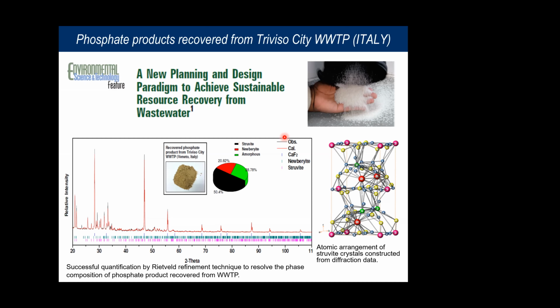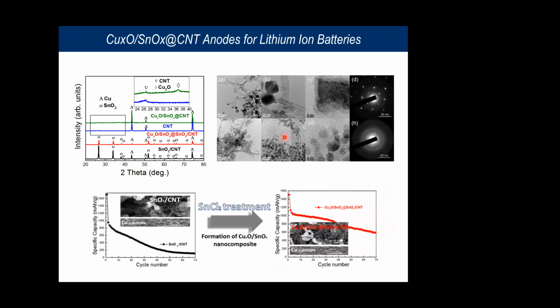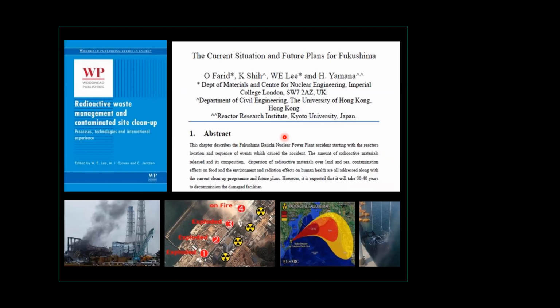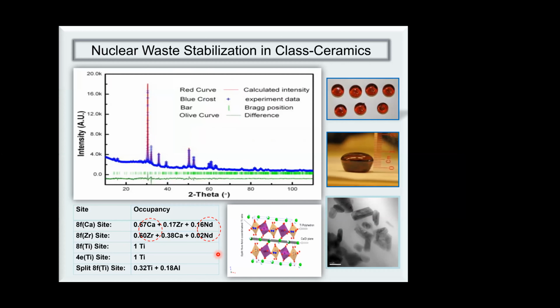And again, using quantitative X-ray diffraction will help you to know how good the recovery of struvite is. We also use this technique to work on a lot of battery materials. It's not necessarily relevant to the environment, but I'm just telling you that anything relevant to minerals, at different scales, at different applications, X-ray diffraction with quantitative capability can also help you. We also use this technique to look at high-level radioactive waste immobilization. For example, you look at neodymium at high temperature in a glass ceramic system, and how the vacancies of the different cations will be occupied by the surrogates of the nuclear waste atoms. It's very interesting to see all these metals moving around at different vacancies, which is directly related to the stabilization effects of the product.